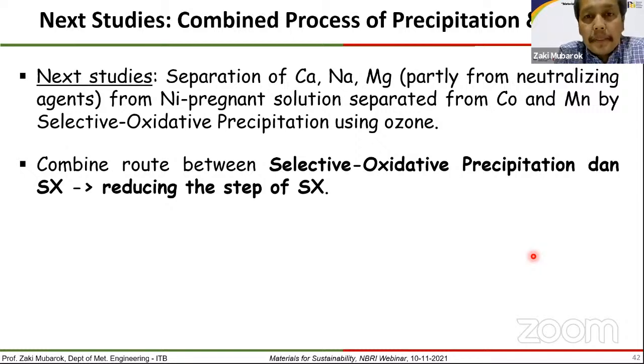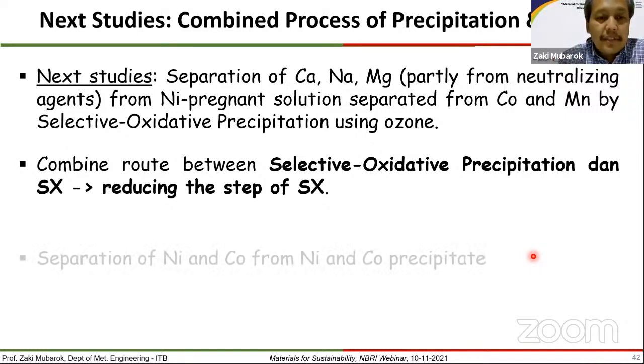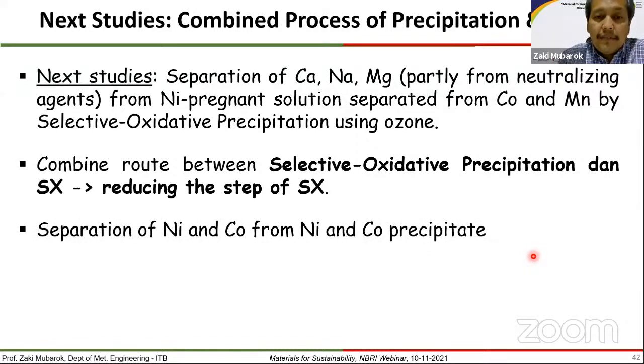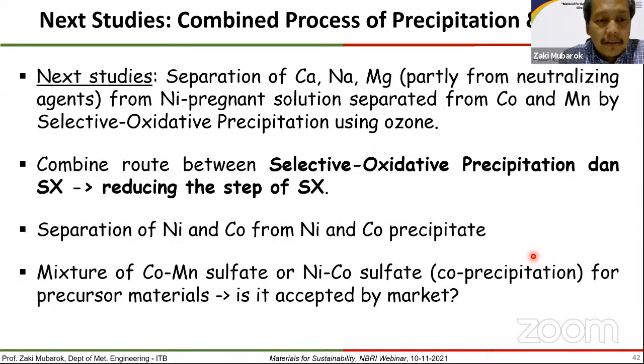But the problem is how to separate nickel from sodium and magnesium, because sodium and magnesium cannot be precipitated by selective oxidative precipitation. Therefore, we thought that we have to combine selective oxidative precipitation with solvent extraction, reducing the step of SX, and also separating nickel and cobalt from the nickel and cobalt precipitate. A mixture of cobalt, manganese sulfate or nickel cobalt sulfate could be a precursor material.